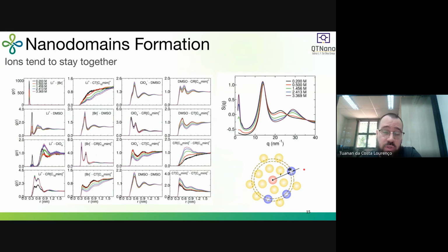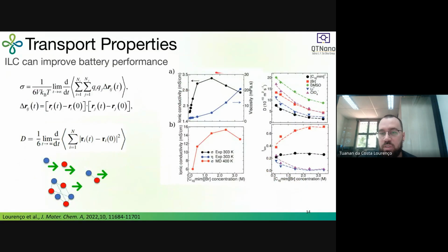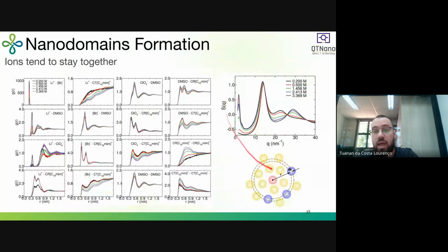As we saw in the beginning of these slides, when we have strong interactions between the ions, probably we have a low contribution to the ionic conductivity, and this is why we see this decrease in the values here. Also, it is interesting when we look at the RDF between the ring of the ionic liquid cation with the ring of the ionic liquid cation, and also between the carbon chains. Here we can see that when we have a small amount of ionic liquid, there is no peak in black here, so no interaction between the cations. But when we increase the concentration, we see the appearance of the peak. That means that the cations are interacting with the cations, and we are seeing the formation of nanodomains in the structure that also contribute negatively to the ionic conductivity.